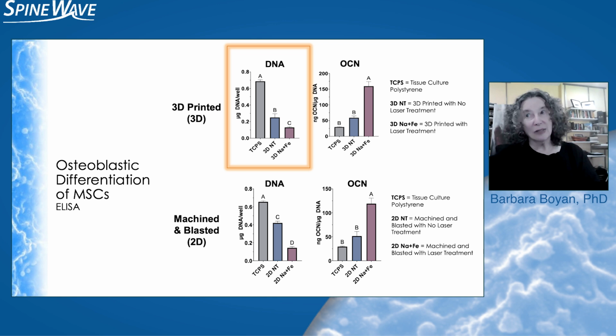Now, that doesn't mean these cells don't grow. They do grow, because you can't have just one cell on a surface and have bone. But by the time we measure them, which is 7 days or 14 days after we put them in culture, the cells have grown onto the surface and they've started to differentiate. And when they do that, they stop multiplying. That's why the actual cell number is less. It's not that they're dying. They're absolutely not dying. They have already gone through divisions, and now they have started to differentiate. On the plastic, they just keep dividing.